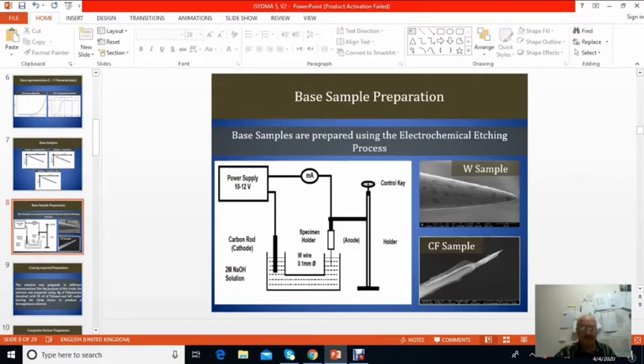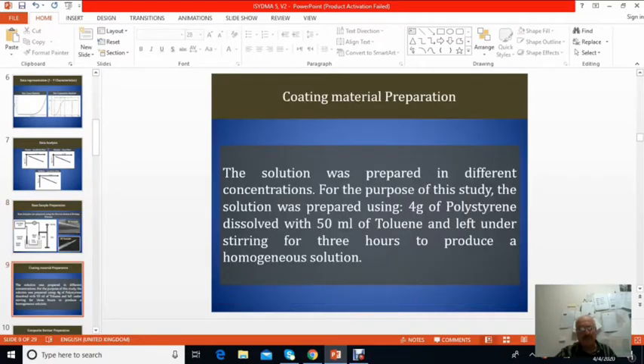Now, the basic sample preparation. This is the sodium hydroxide solution. The composition, the concentration differs if it is metal or carbon fiber. So this is the cathode, which is a carbon rod, and this is the anode, which is the tip immersed to here until we have a power supply, and sometimes we have a switching device by which, when it is etched, when we turn on the power supply at certain current, it cuts at this point and produce this sharp tip. This is the tungsten sample, and this is the carbon fiber sample. Of course, it is known that it is much more difficult to work with carbon fiber samples. So it's a huge effort from our team to work on these carbon fibers.